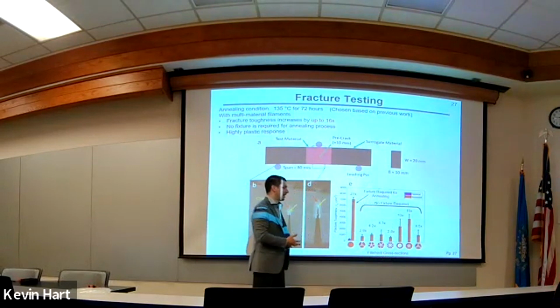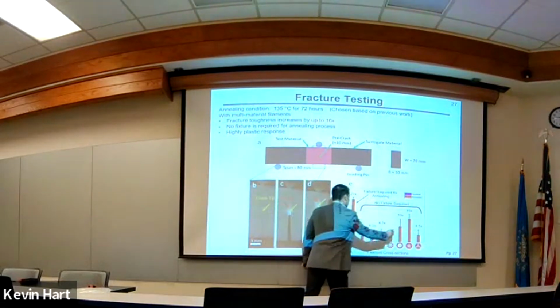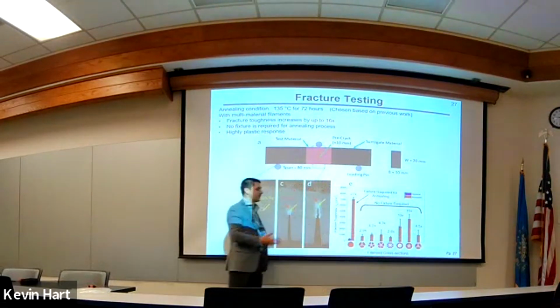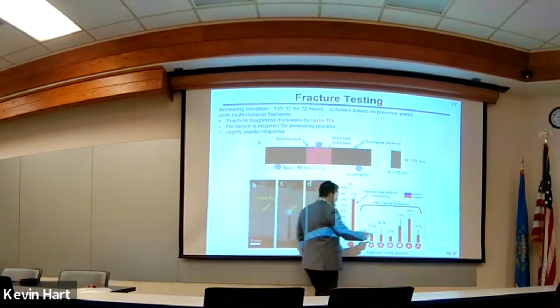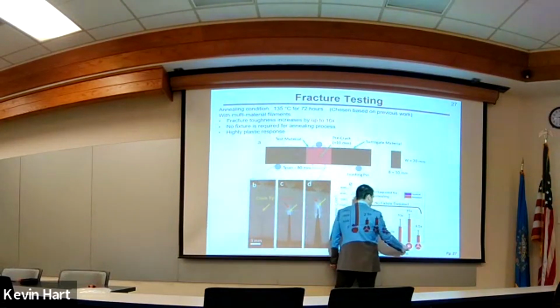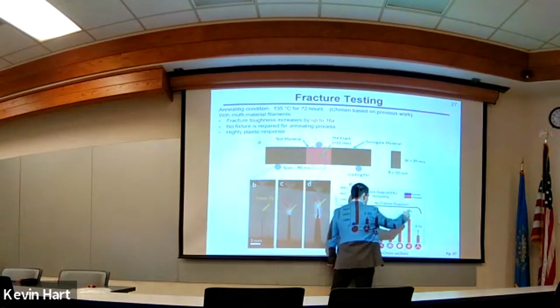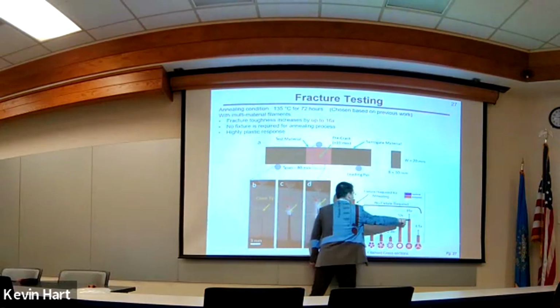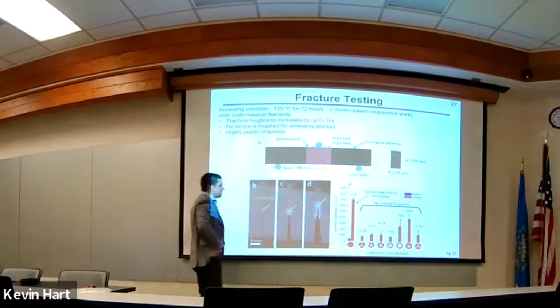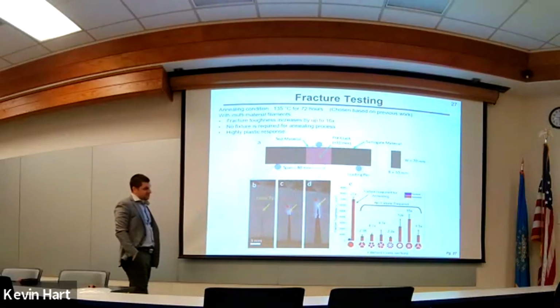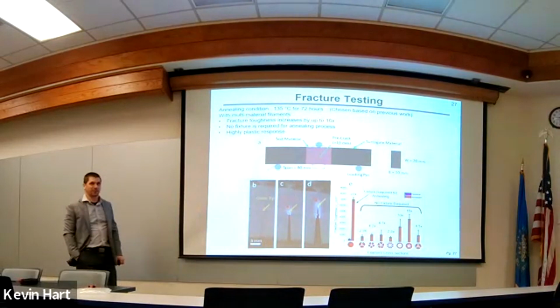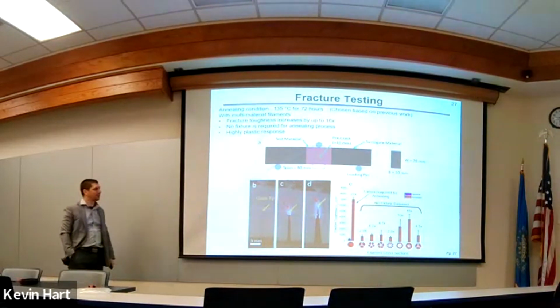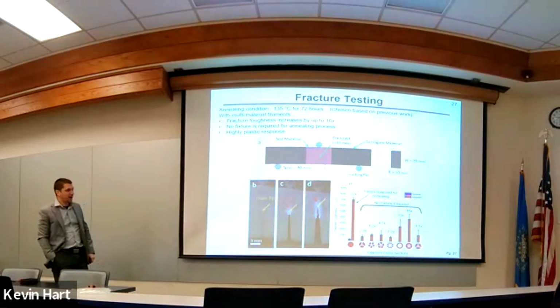using the various filament geometries; we made a lot of different types. The best performer was this star-shaped filament that looks like this, and that gives us 16 times the nominal toughness, and you get about 4,000-ish joules per meter squared, which is getting to injection molded levels. Basically, we've achieved injection molded levels. All right, so pretty awesome.